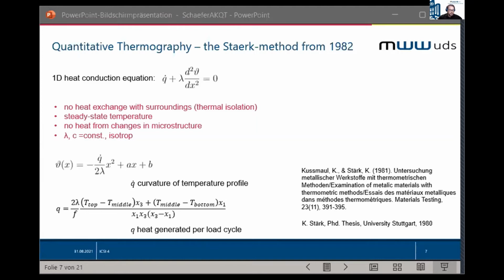So if we now consider just this simplified one-dimensional heat equation, and we assume that there is no heat exchange with the surroundings, so we have a good thermal isolation, that we measure a steady state, and we have no heat from changes in the microstructure, and the thermal conductivity tensor is constant, and so on, we get the simple solution of this one-dimensional heat equation. It's just a parabola. Already in 1982, Klaus Stark proposed this method in his PhD thesis, but it was never published in English. We can get an idea of the shape of the parabola just from 3 distinct measurement points.